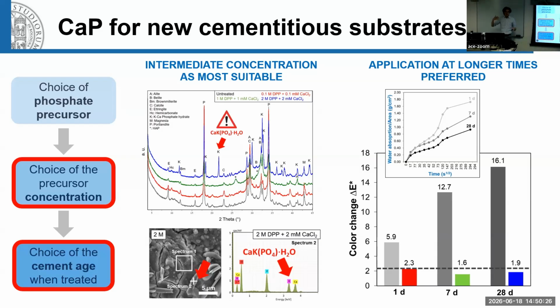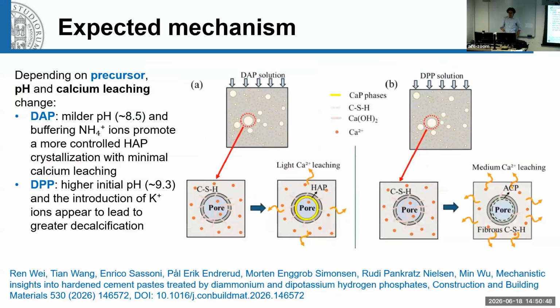least 28 days. So you need to allow curing time for the cement, because if you apply the phosphate treatment like after 1 day or 3 days, then the phosphate treatment interferes with the hydration of the CSH. So there's some competition between these two processes, so it's best to apply it at a later stage.